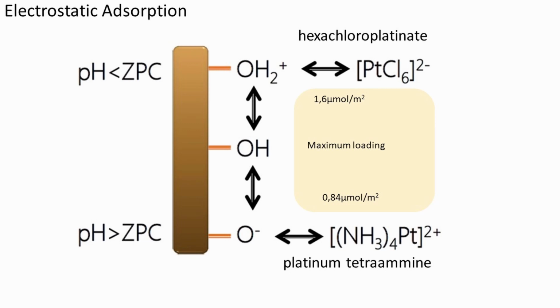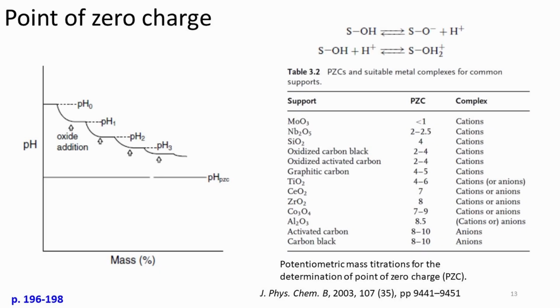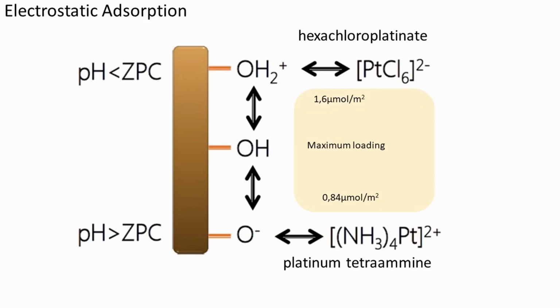At low pH, the hydroxyl group will pick up a proton from the solution and become positively charged. At elevated pH, deprotonation of the OH group will give rise to negative charge. The pH at which the net charge of dispersed oxide particles is zero is referred to as the point of zero charge. Point of zero charge values for common support materials are listed in the table. As indicated in the figure, at pH less than the point of zero charge, anion adsorption prevails, whereas at pH more than the point of zero charge, cation adsorption is dominant.